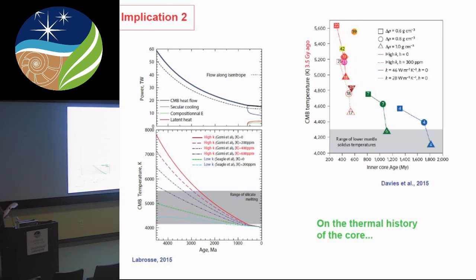that we have a heat flux of 15 terawatts. Labrosse suggested, and Davies suggested basically the same, that you have to assume the core has been removing heat from its body for a long time at the pace that is rated here. And this means a lot of heat should be stored in the core initially. So these are different models using different conductivity values for the outer core, with high conductivity values here leading to a very hot core in the past, because along the core adiabats, if you have a high conductivity, you remove a lot of heat simply.